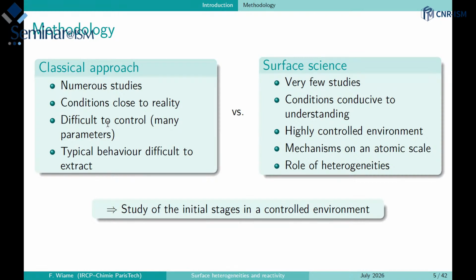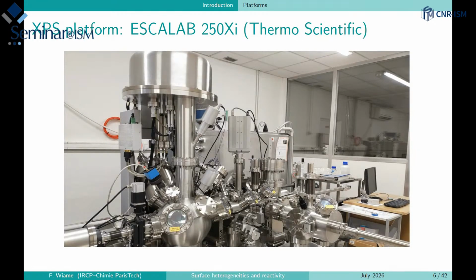So our approach is surface science, where we have much less experiments, but we try to work in a highly controlled environment in order to understand the very fundamental mechanism of reaction on these optimized and simplified model structures. And the idea is to identify the mechanism of reactivity at the atomic scale and to see what are the parameters that are influencing. In fact, we can see that the heterogeneities that you have at the surface are really important and essential to understand this reactivity. And this is the reason why we study the very initial stages in a very controlled environment to try to understand this mechanism.